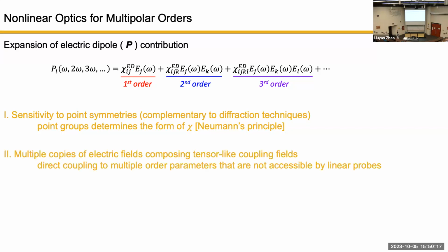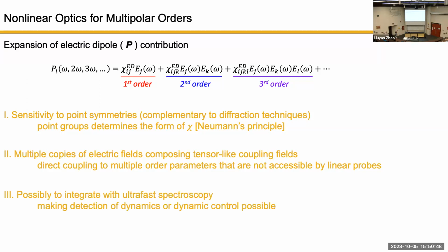Okay, that's one benefit. The second benefit is, as we have been repeating over the past few minutes, that if I have multiple copies of the electric field participating in this process, I can use multiple copies of the field, which are vectors, but their combination are tensors. So effectively through this process, I'm constructing a tensor field and then using a tensor field to probe a tensor order. That makes more sense and makes things easier. Okay, so that's the second benefit. The third benefit is that since we are using very short pulses, we can actually measure dynamics, especially quick dynamics. The integration with dynamic measurement is natural with this technique.